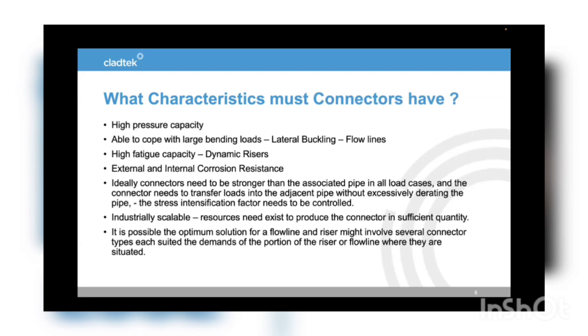To be used in oil and gas services, what kind of characteristics do connectors need? Typically, we're looking for high pressure capacity and high reliability, resistance to leaking, able to cope with large bending loads, so that's the loads during installation, lateral buckling. In the case of risers, a high fatigue capacity, internal and external corrosion resistance. So internally, the connector needs to be protected from the well fluids that are coming through the pipeline or riser, and externally, seawater ingress into the threaded areas or the areas that mechanically lock together is also important for the integrity. So they need internal and external corrosion resistance, and that's mainly achieved by coatings, water resistant seals, so environmental seals, and anodes.